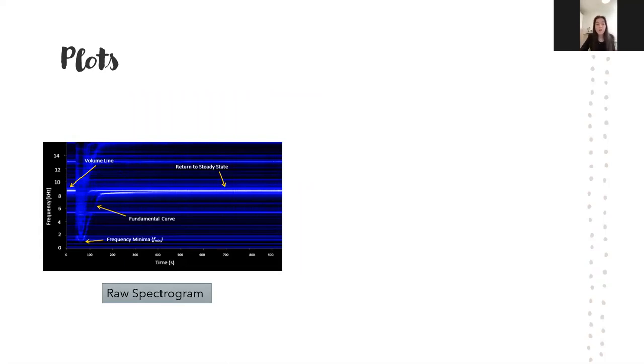So the acoustic profile of interest is called the fundamental curve. So the F-min, or the frequency minima, represents an equilibrium between the rate of gas formation in solution and the rate of gas release at the surface. In BARDS analysis, the fundamental curve is used to make comparisons between individual experiments. The volume line is recorded for the first 30 seconds to establish the resonance frequency of the glass vessel and its associated 25 mL of solvent, which is typically a weak acid, a weak base, or even just deionized water. Organic solvents are usually steered away from. Once the sample is added, the resonance frequency decreases to the frequency minima, followed by a return to steady state, marking the full dissolution of our sample.